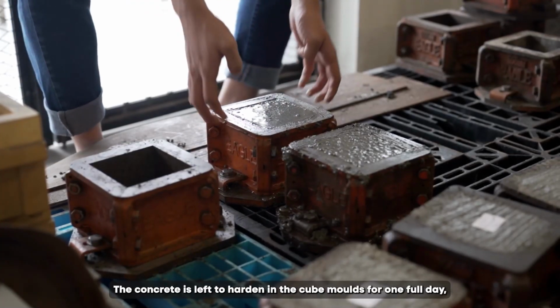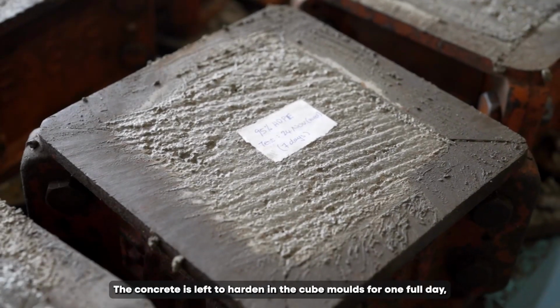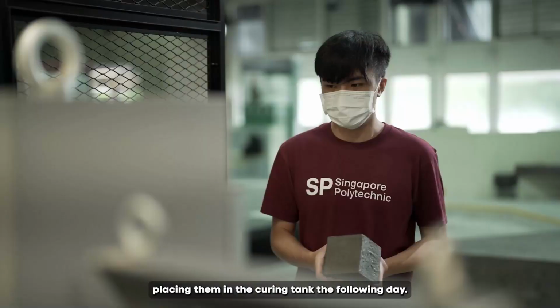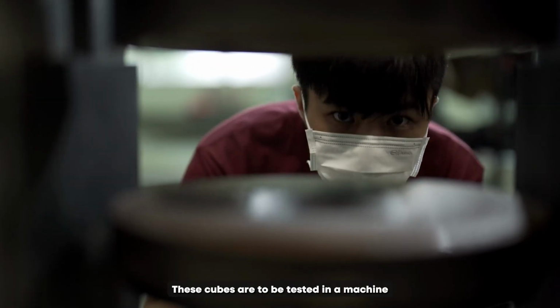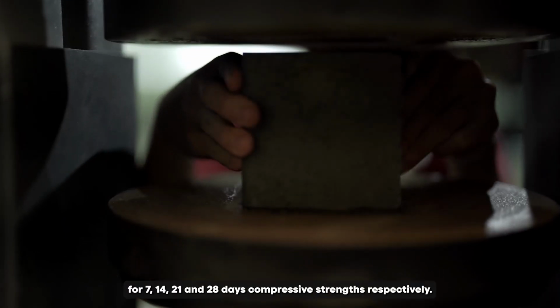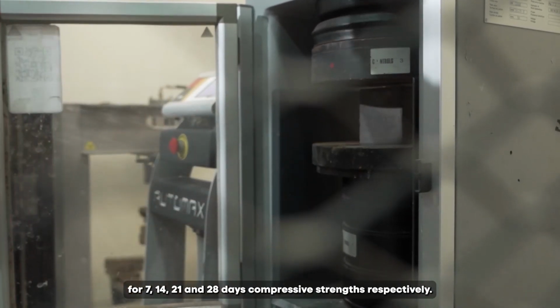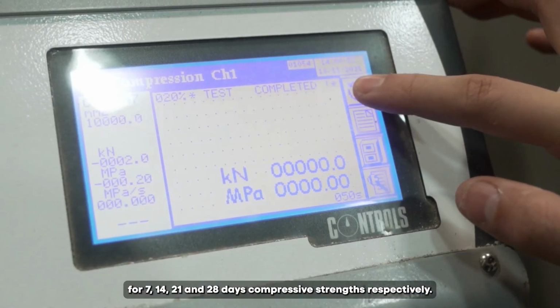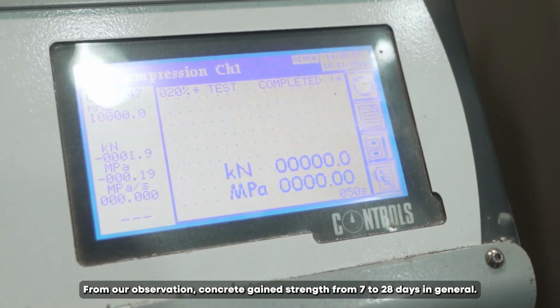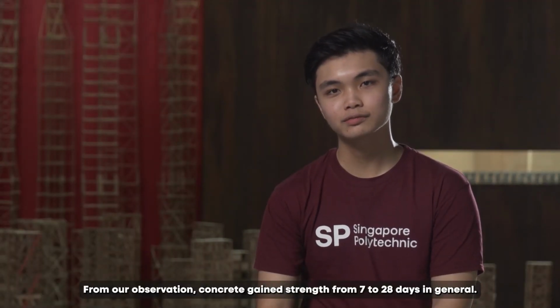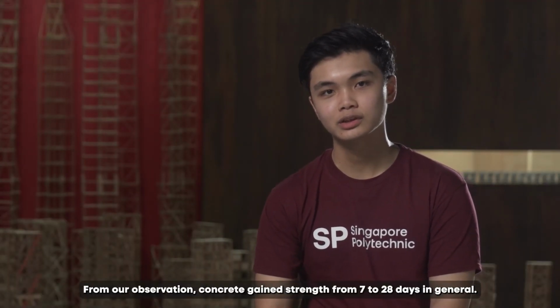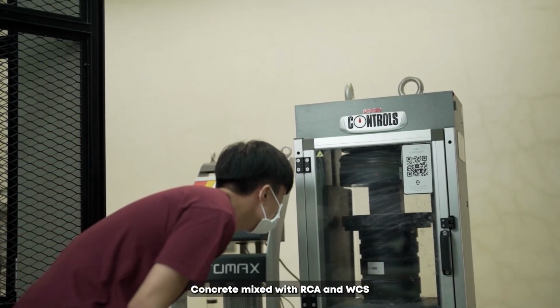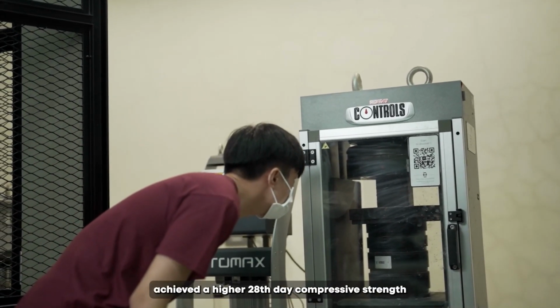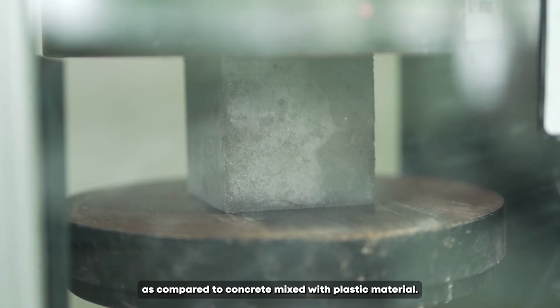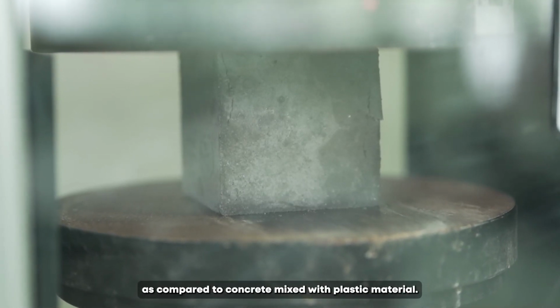The concrete is left to harden in the cube molds for 1 full day, placing them in the curing tank the following day. These cubes are to be tested in a machine for 7, 14, 21 and 28 days compressive strengths respectively. From our observation, concrete gains strength from 7 to 28 days in general. Concrete mixed with RCA and WCS achieved a higher 28th-day compressive strength as compared to concrete mixed with plastic material.